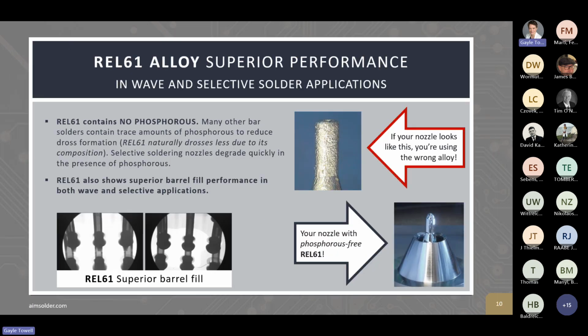It also works very well in wave and selective soldering applications. Of note is that there's no phosphorus added to it. Sometimes people will add phosphorus to bar solder in order to mitigate dross formation, but REL61 naturally forms less dross due to its composition, so there's no phosphorus added. One of the drawbacks of phosphorus, particularly in selective soldering, is it can degrade the nozzles. So that's not an issue with REL61.